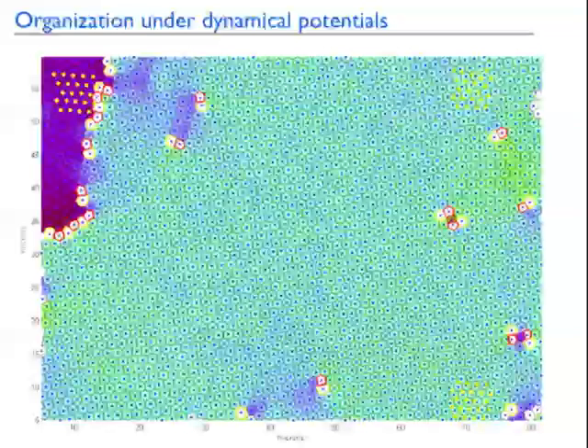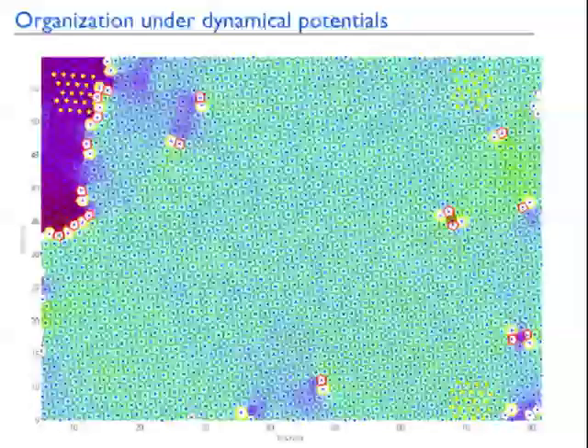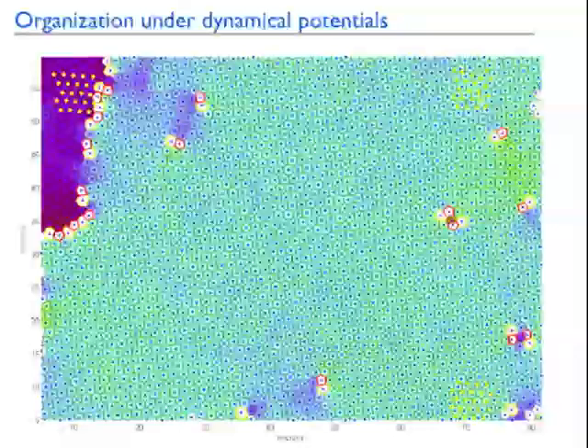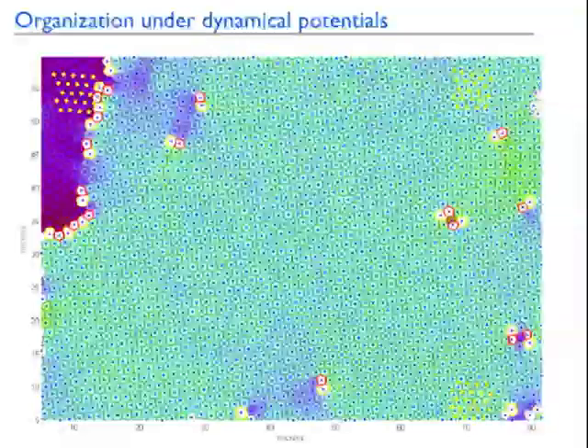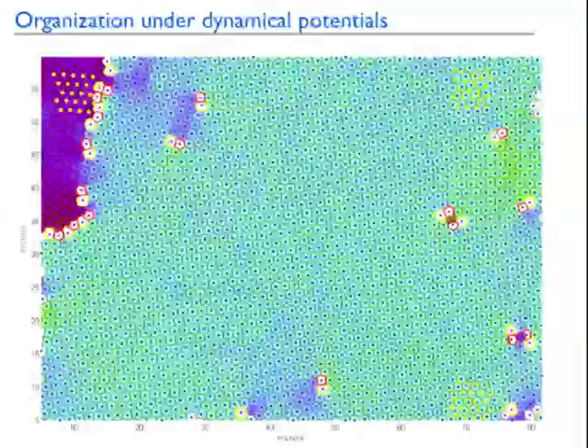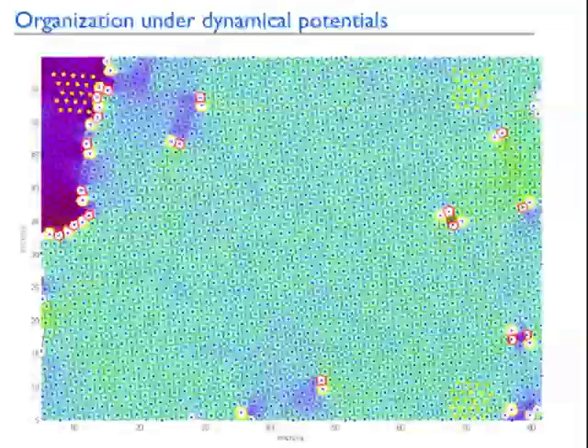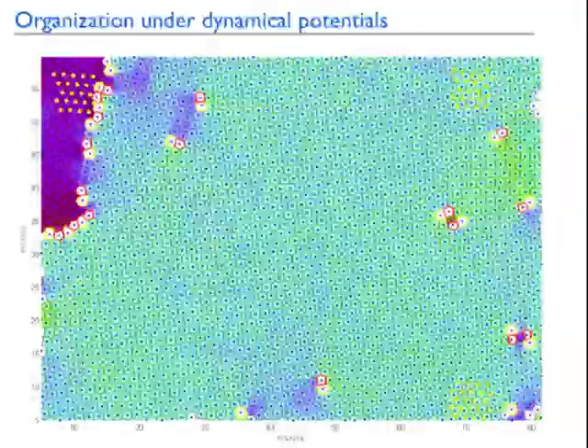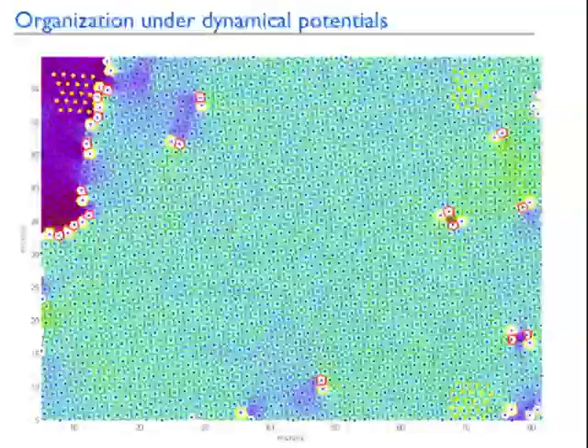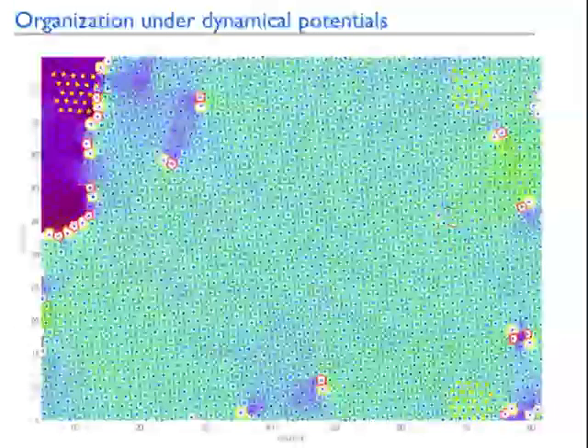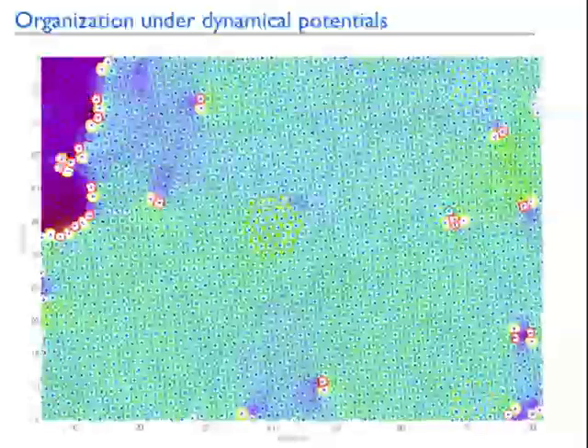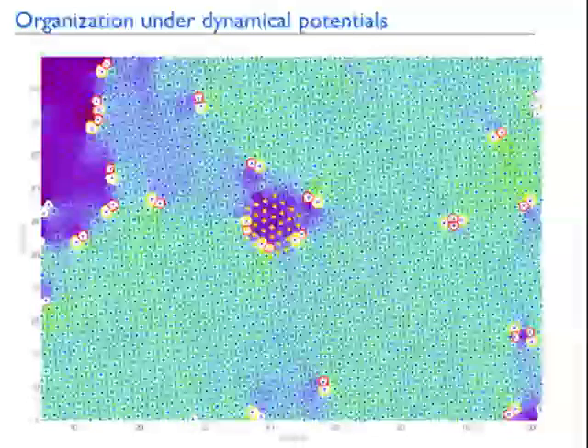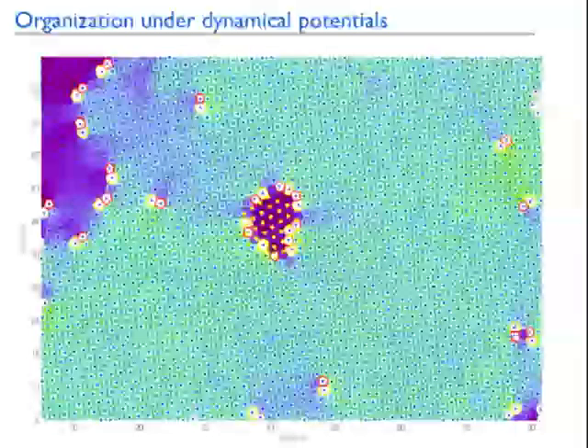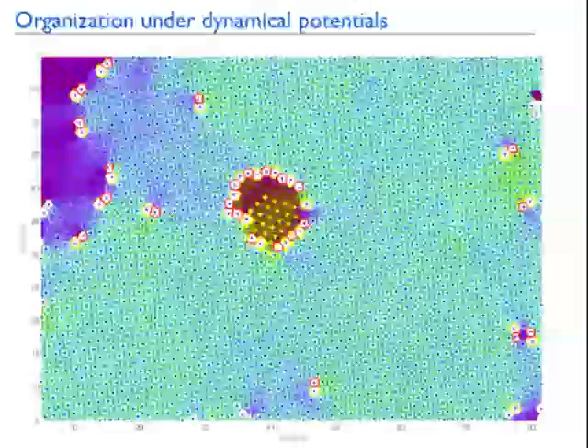This was actually really cool, but I'm not going to go on with it very much, because it tells you something about the intrinsic property of dislocations, or about plasticity in solids, which is that it's irreversible. What we're going to do here is take a perfect region of the sample. We're going to grab it like this and twist it, and that should make a domain. A domain is something with a different orientation, and it will be a grain. It will have a grain boundary around it. And you can actually watch the grain boundary form as you grab it and you twist like that. It creates dislocations. The dislocations make a grain boundary around it.